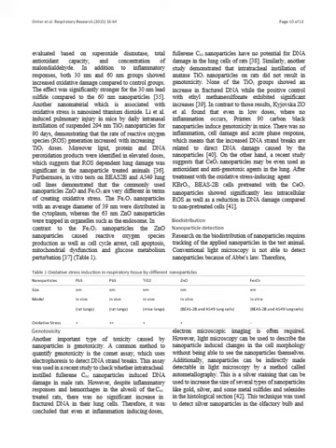Another nanomaterial which is associated with oxidative stress is nanosized titanium dioxide. Lee et al. induced pulmonary injury in mice by daily intranasal instillation of suspended 294 nanometer titanium dioxide nanoparticles for 90 days, demonstrating that the rate of reactive oxygen species generation increased with increasing TiO2 doses. Moreover, lipid, protein, and DNA peroxidation products were identified in elevated doses, which suggests that ROS-dependent lung damage was significant